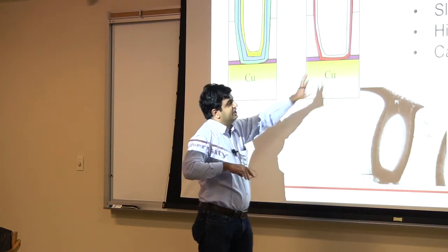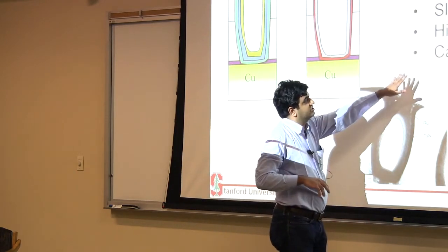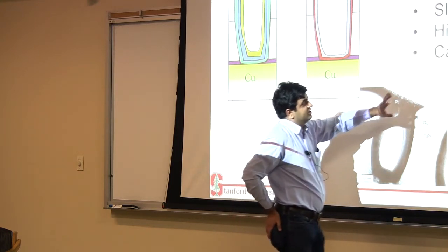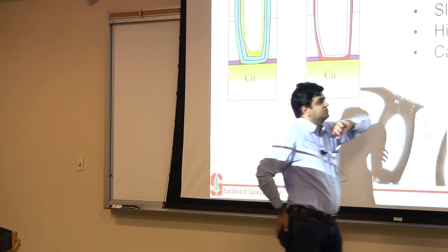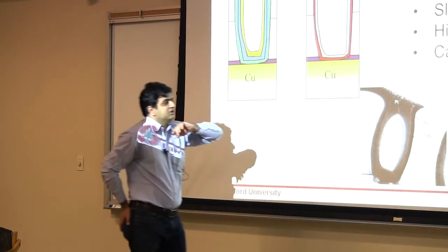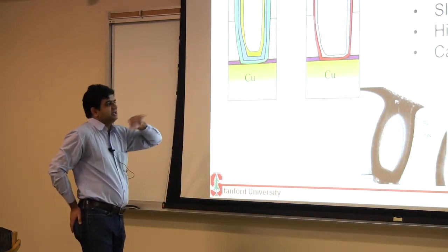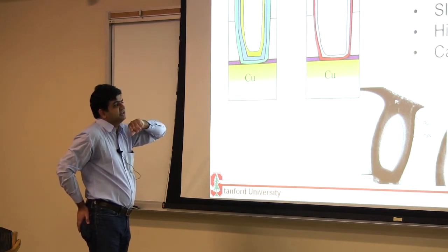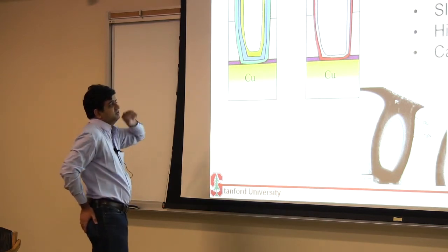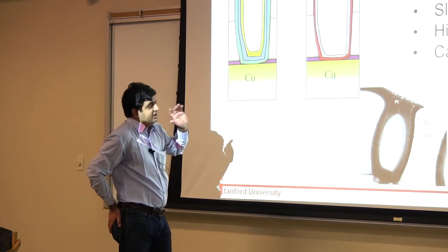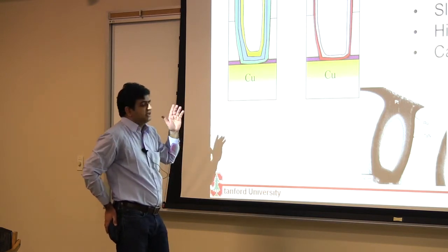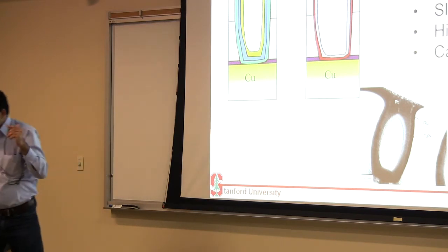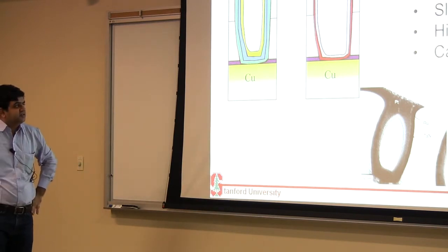And at best, even if they all leave the surface, you are left with carbon contamination on the order of 1e16, 1e17 atoms on your surface, and that essentially again increases the resistivity of your film. So even though you're depositing metals, they end up with resistivities that look like they are dielectrics. So that's a disadvantage of ALD.